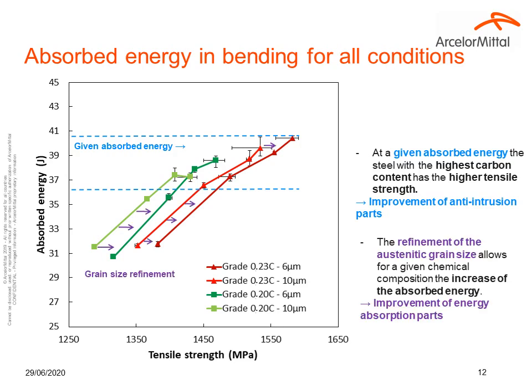However, if you look at the effect of the grain refinement due to the different heat treatment parameters, you can see that this refinement allows, for a given chemical composition, an increase of the absorbed energy. This could improve the mechanical parts responsible for energy absorption in a crash.